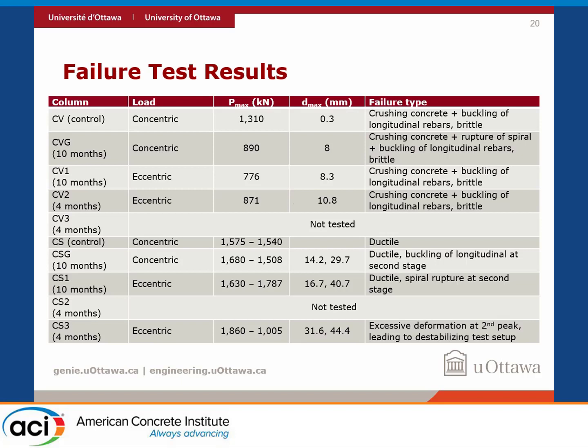The only exception was the last one, which we believe is not representative of what happened, because there was a lot of deformation when attaining the second peak, and we believe that deformation had to do with yielding of the beam that was transferring the load. So we don't consider that as very representative of the other three specimens.